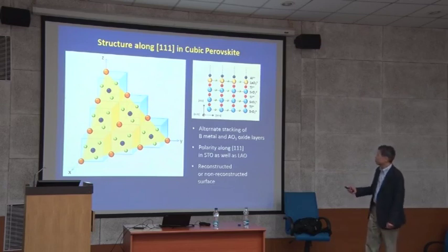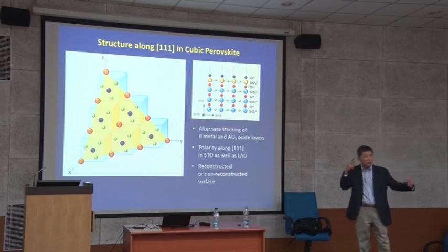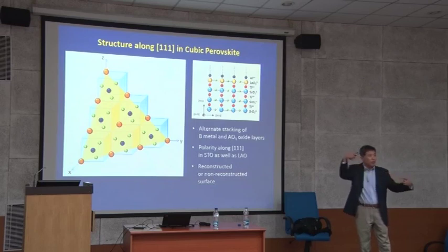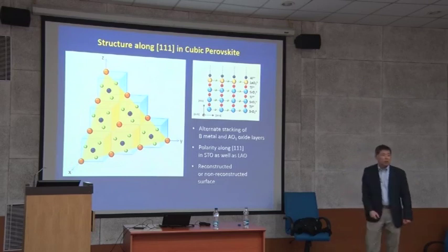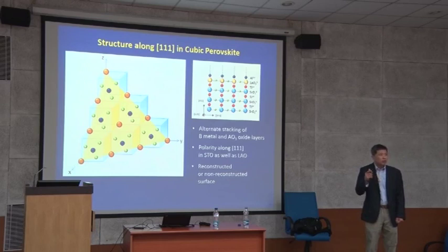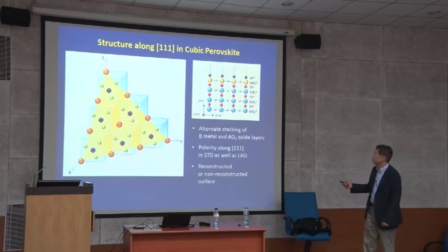And this bilayer, one strontium oxide 3 and one titanium, is one third of the body diagonal direction. You understand that? Along the body diagonal direction you can stack 3 bilayers. So the actual length is one third of the square root of 3 times the lattice parameter, roughly 2.2 angstrom rather than 4 angstrom. So that's 2.2 to 2.3 angstrom, and this one is roughly 4 angstrom.